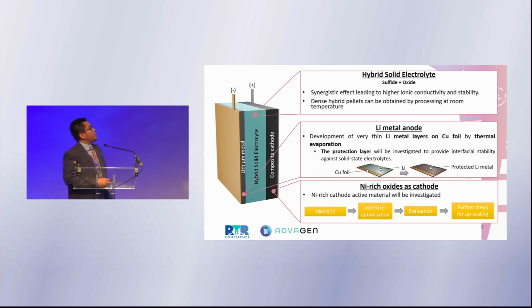The idea for the ADVAGEN project is that we want to develop these 3 battery components. The first one is a hybrid solid electrolyte. If we follow the previous presentation about hybrid solid state electrolytes, mostly they have a different definition, with inorganic and polymer and others. But here our definition is to mix solid sulfide and oxide solid electrolyte, to utilize the synergistic effect leading to higher ionic conductivity and stability. In this case, we take the high ionic conductivity from the sulfide, and we utilize the mechanical stability of the oxide. Dense hybrid pellets can be obtained by processing at room temperature, which has been done in lab scale in the coin cell as well.